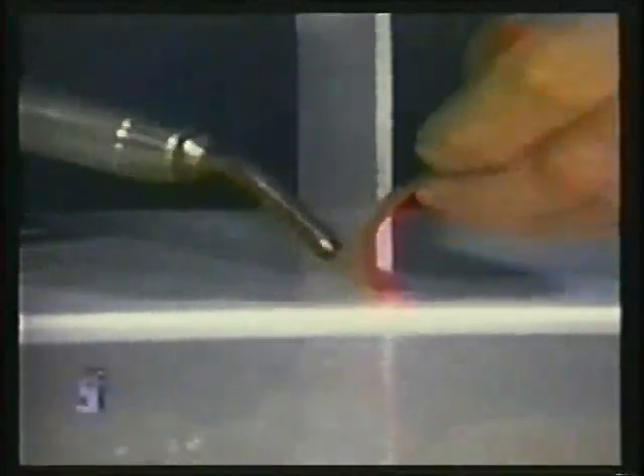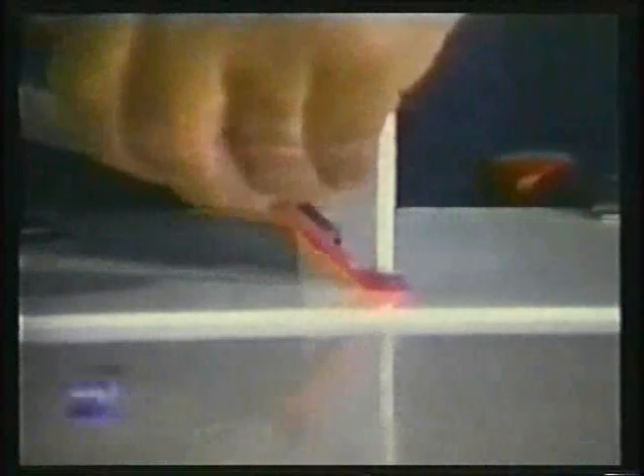When welding an outside corner, some key points to remember are: be sure that your welding rod is at a vertical angle to the weld. Keep a steady fanning motion of heat on the welding rod and the base material, and a steady downward pressure on the welding rod, checking for small beads of juicing. If pressure and temperature are correct, a slight juicing on each side of the welding rod should appear. A steady motion around the corner will result in a perfect weld bead.